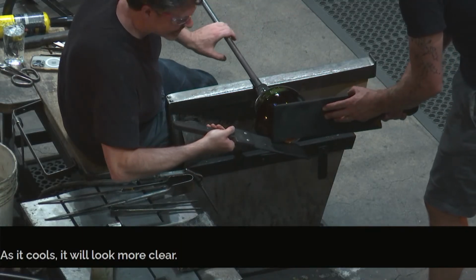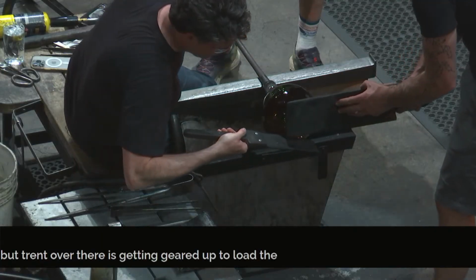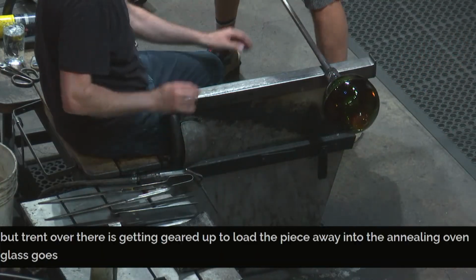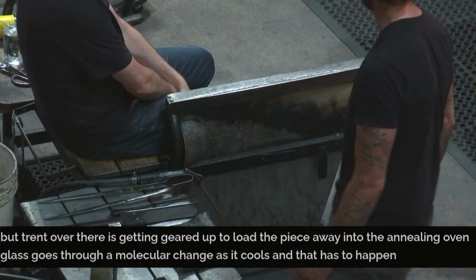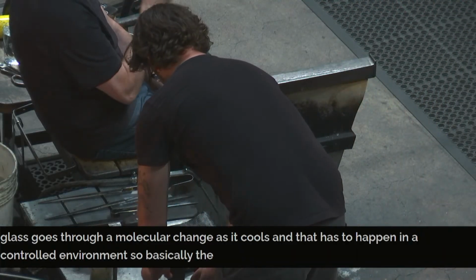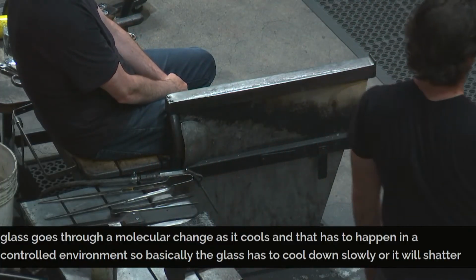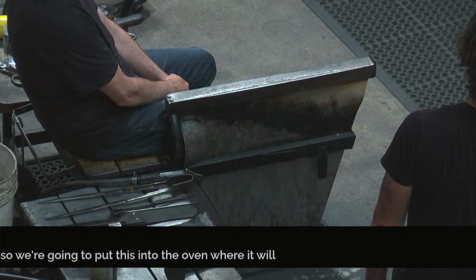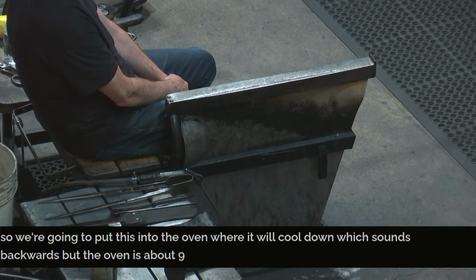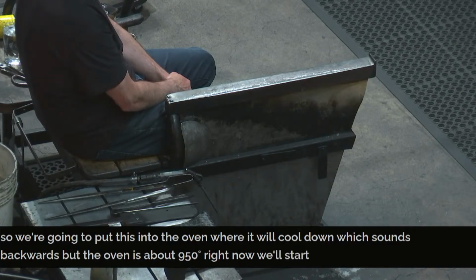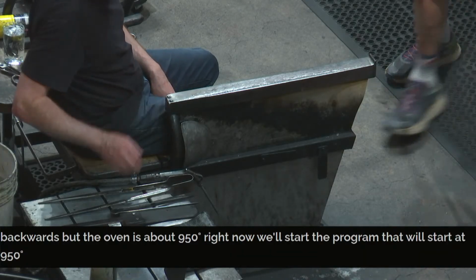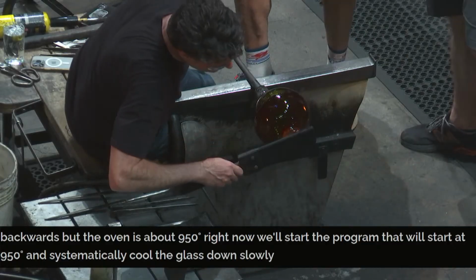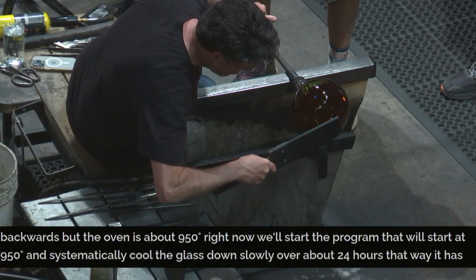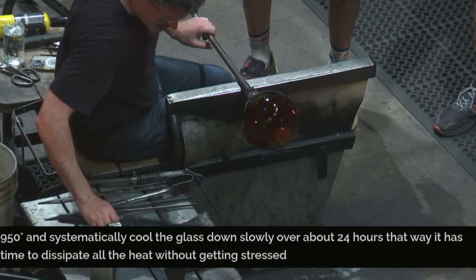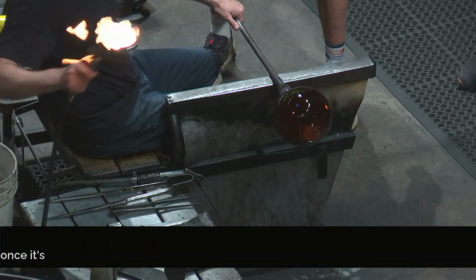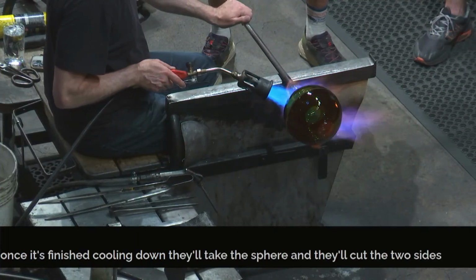But Trent over there is getting geared up to load the piece away into the annealing oven. Glass goes through a molecular change as it cools, and that has to happen in a controlled environment. So basically, the glass has to cool down slowly or it will shatter. So we're going to put this into the oven where it will cool down, which sounds backwards, but the oven is about 950 degrees right now. We'll start the program that will start at 950 degrees and systematically cool the glass down slowly over about 24 hours. That way it has time to dissipate all the heat without getting stressed and breaking. Once it's finished cooling down, they'll take the sphere and they'll cut the two sides of it off to make something like this.